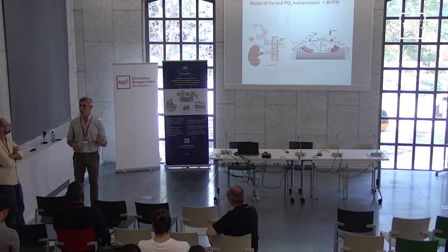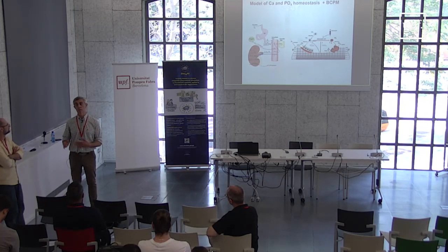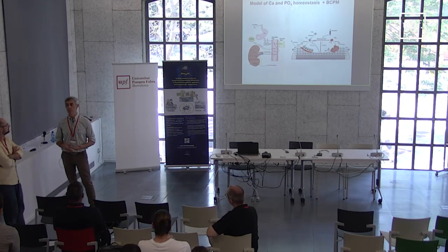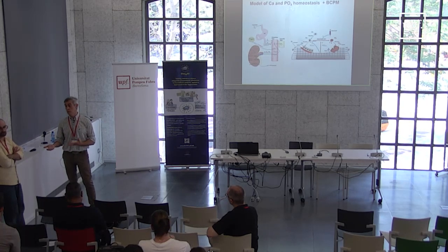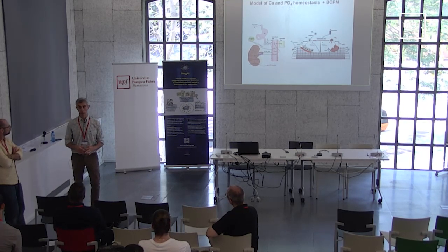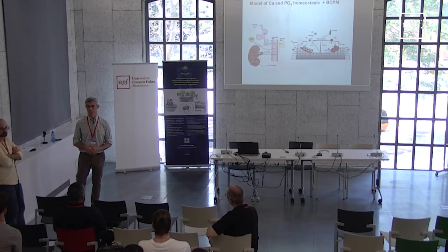And in the case of cortical bone, this is key. In the case of trabecular bone, I would say the quality of microstructure is the key point. And the reduction of bone volume, the increase of porosity, is more significant in trabecular bone than in cortical bone.